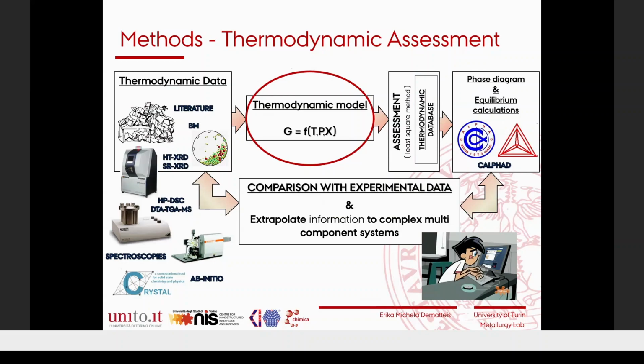Once we collect all the thermodynamic data, we perform an assessment. So we try to model the Gibbs free energy of the different phases, structures and compounds by a parametric description of the Gibbs free energy as a function of temperature, pressure, and composition. By this assessment, we can build up thermodynamic databases using the CALPHAD approach. With the CALPHAD approach, we can do phase diagram calculations using this developed thermodynamic database, and also equilibrium calculations that allow us to calculate and compare this data with the experiments we have collected in the literature. So we are closing this cycle, and we are also able to extrapolate information towards more complex systems.